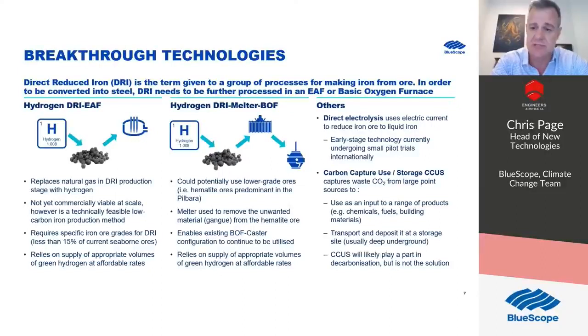Now, it's mostly metallized, so you still have some impurities in it, which, if the quality of the iron ore is good enough, you don't have to do a lot of work to remove. So primarily, if people want to use the hydrogen DRI EAF process, they have to have a high quality ore, and that's typically called magnetite iron ore. Magnetite iron ore has a higher iron content and a lower residual content, which enables it to not create a lot of slag and therefore be amenable to the electric arc furnace process. But at the moment, of what's mined in the world, only about 15% is magnetite.